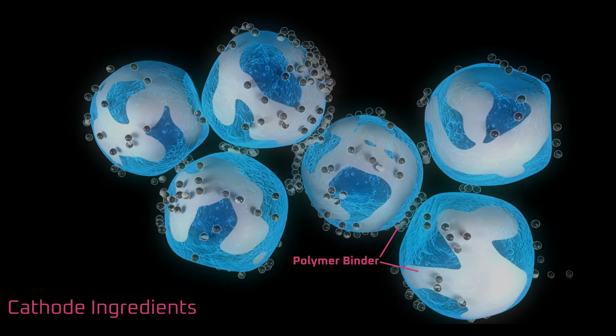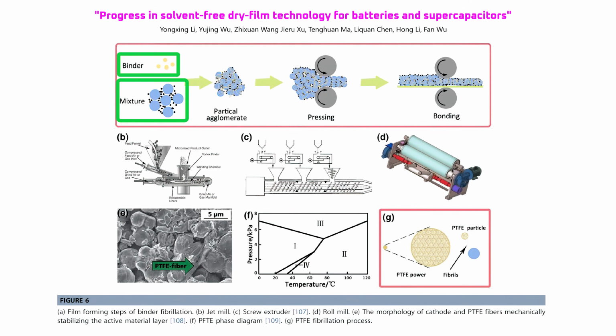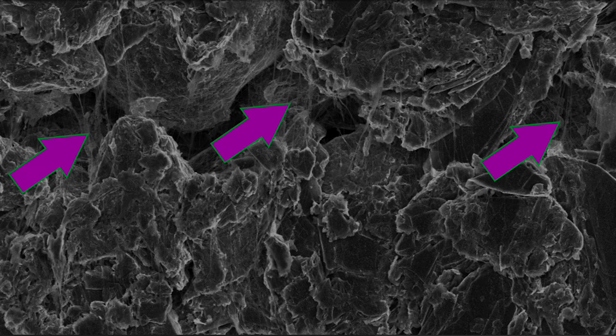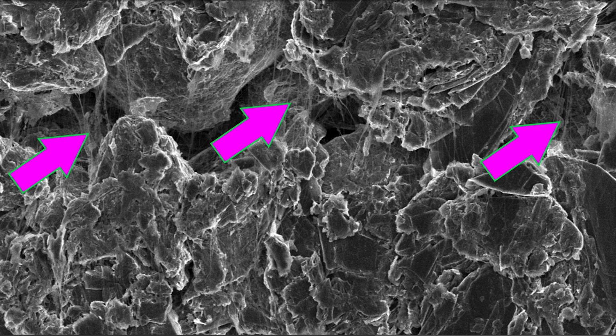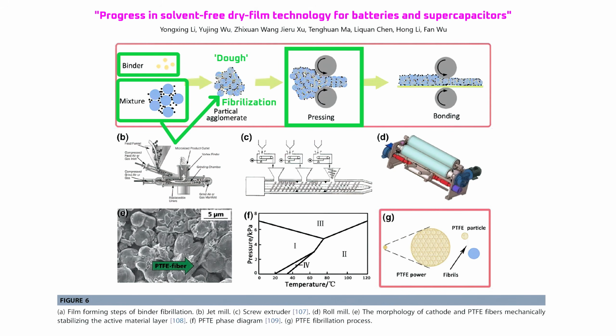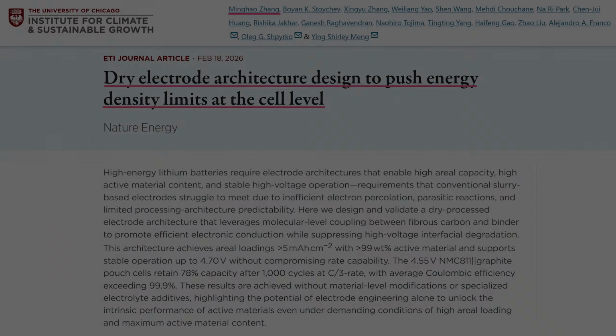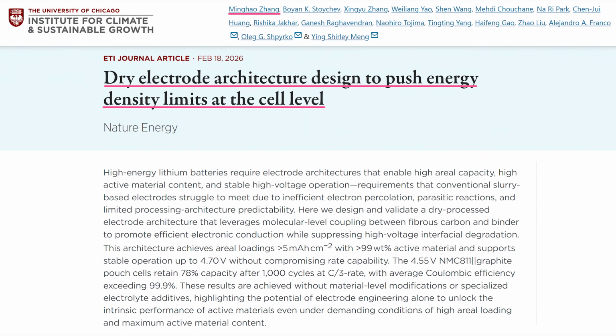Tesla's dry process also starts by mixing cathode powder, carbon powder, and a binder powder, but the binder used is PTFE, also known as Teflon. When PTFE is exposed to shear forces and heat, it fibrillizes like bubblegum into spider silk-like filaments that turn the powder mixture into a kind of dough, which is heated and compressed to form a cathode film. No drying required.